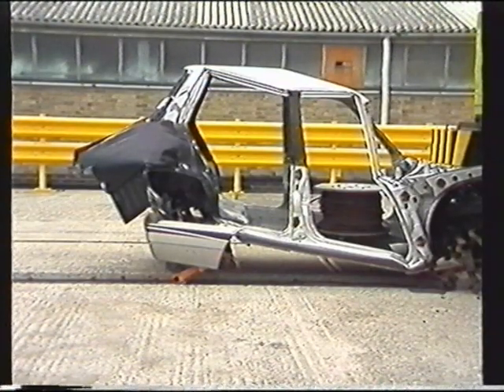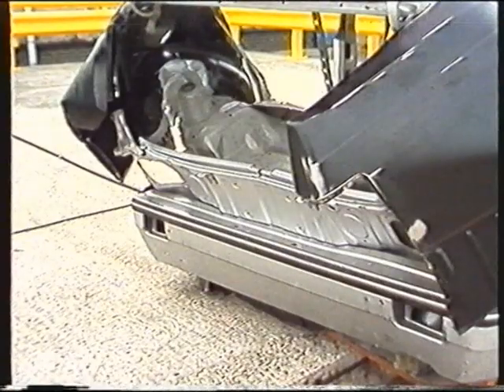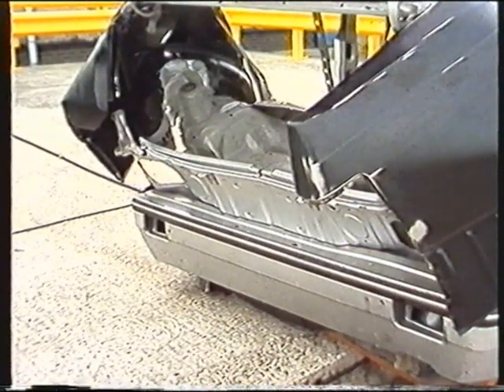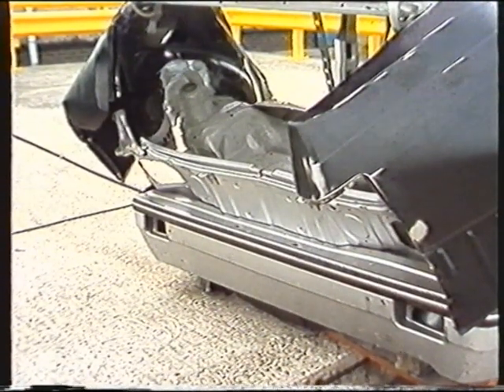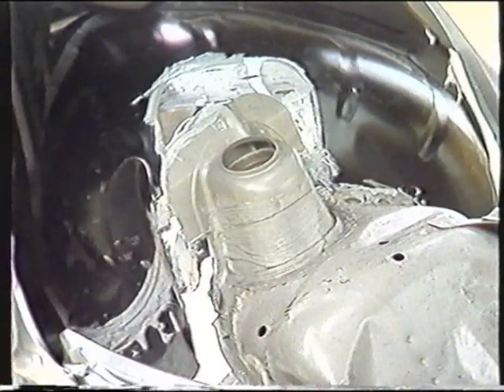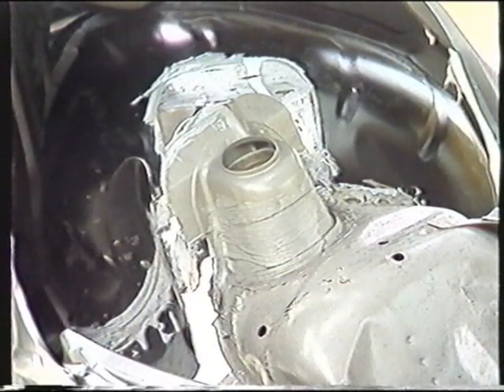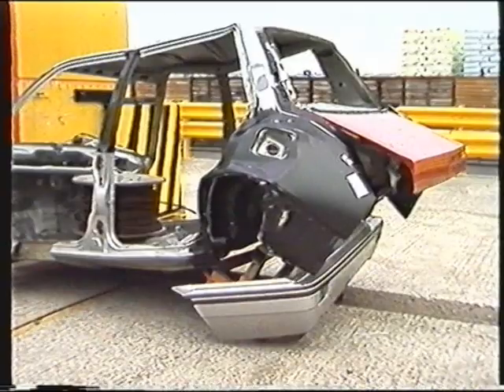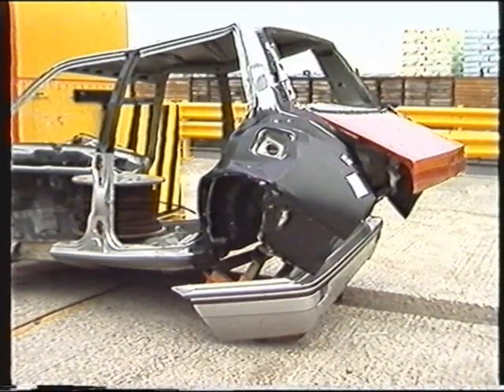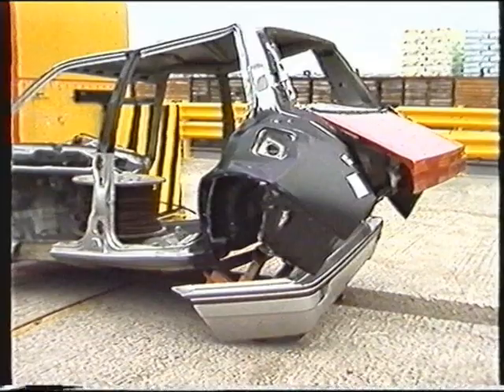On examination, it was found that although delamination had occurred, the impact had caused no significantly greater damage to the vehicle than if the joints had been resistance welded. Weld bonding of the joints on both these Rover 200s had been found to be preferable to just using an adhesive. Adding a limited number of spot welds to a bonded joint greatly increases resistance to separation by peeling.